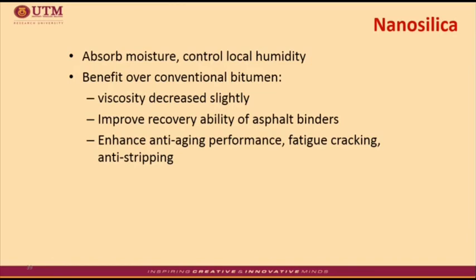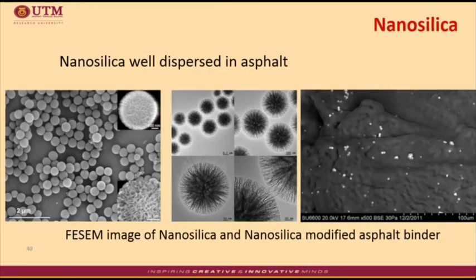Adding nanosilica to the base asphalt binder slightly decreases the viscosity values of the asphalt binder. The low viscosity of the asphalt binder indicates that a lower compaction temperature or lower energy consumption can be achieved during the production process. Adding nanosilica to the asphalt was found to improve the recovery ability, stress properties and relaxation capacity of the asphalt. Nanosilica also enhanced the anti-aging performance, fatigue cracking and anti-stripping. This slide shows the micro images of nanosilica and its dispersal status in a given asphalt matrix. From the image, the nanosilica seems to be well dispersed in the asphalt.